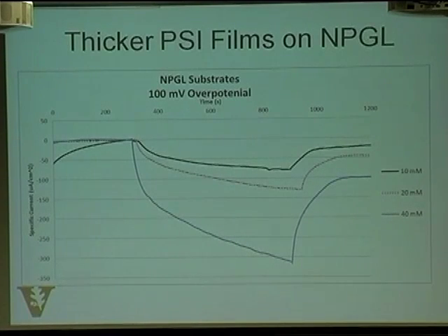So photocurrents now. Before, I showed you a maximum, I think, of 10 microamps per centimeter squared. These new results show us going up to, if you take, say, the line connecting that blue curve, an average of maybe 200 microamps per centimeter squared there.